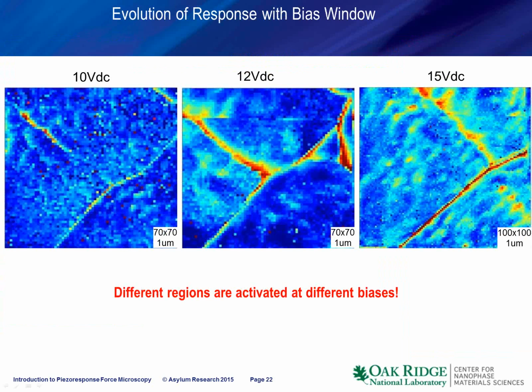This is illustrated on this slide, where we take these maps with different bias windows, and you can see that at 10 volts, our hysteresis loops are open on one grain boundary, start to open on another one, and there are a number of hotspots and waviness within the grains themselves. If we increase our bias window to 12 volts, then all of a sudden we start to see stronger hysteresis loop opening on one of the grains and smoothening of the contrast within the silicon grains. And finally, for 15 volts, we see that the hysteresis loops are open primarily on one of the grain boundaries and relatively less pronounced on the other.